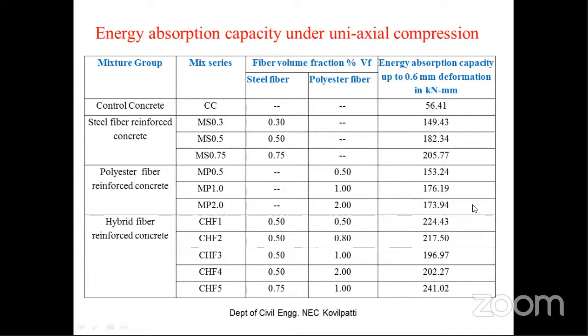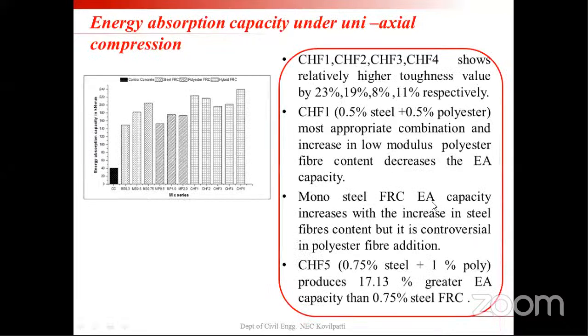So again, you can notice in hybrid FRC, the energy absorption capacity is in the range of 196 to 241. And in steel FRC, it is 149 to 205. Control concrete without fiber, just 56. It doesn't absorb any energy. And polyester fiber is also enhanced, in the range of 153 to 176. So this is a comparison study with the help of the graph I have shown.